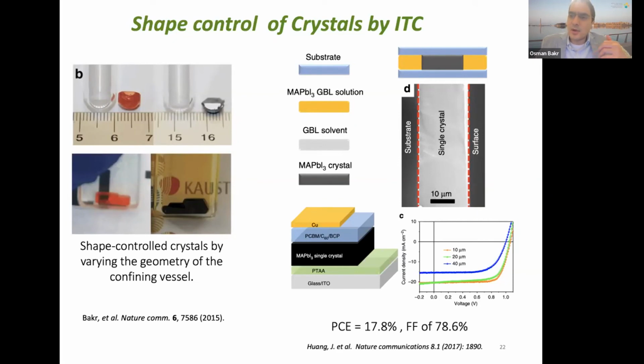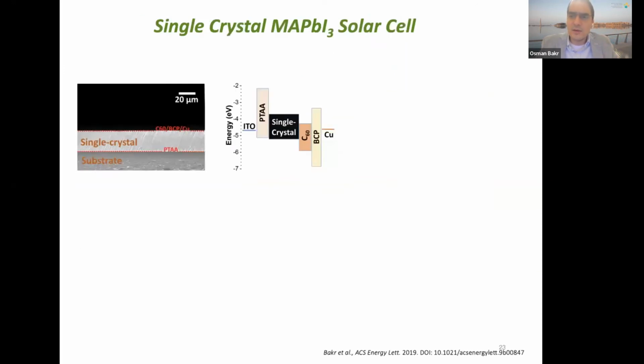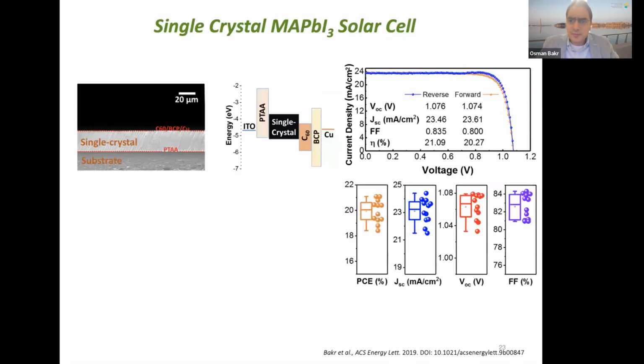However, we thought that if we can control the growth, we can control the interface quality better, we could actually start looking at improving the devices to the level where they could really compete with the best devices out there. And that's what we did. We controlled the interface, we controlled the temperature, and we did the growth at conditions that are oxygen free. And what we found is that actually the solar cells are as good as the best thin film solar cells, but in fact they're almost 100 times thicker.